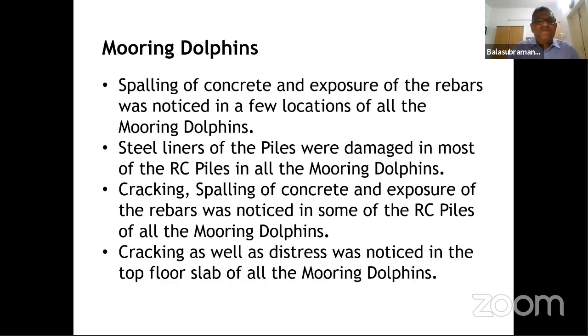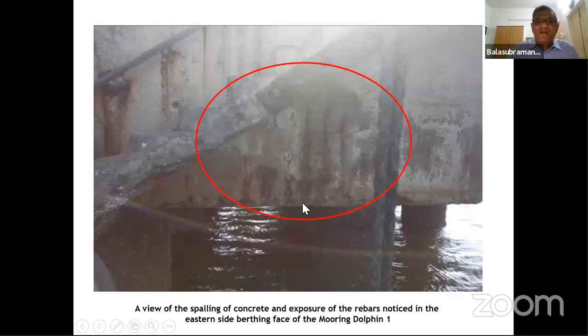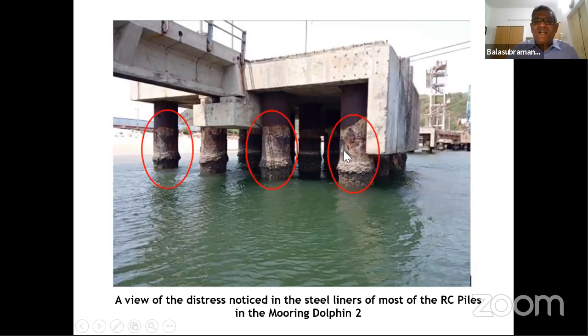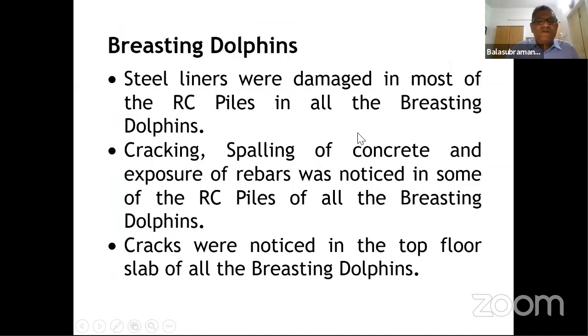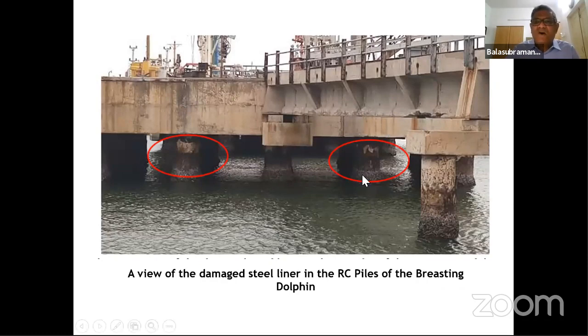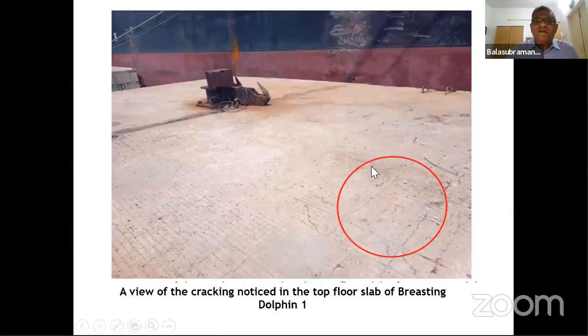We found in the mooring dolphin RC piles, steel liners were damaged, spalling of concrete, exposure of the rebars, for example, exposure of rebars, and all the steel liners of the piles of the mooring. This is a mooring dolphin. They're damaged. And if you look into the breasting dolphin, again, steel liners were damaged in the RC piles, cracking, spalling of concrete, and then cracking was noticed in the top floor of the slab. See here, you see all the steel liners were damaged. Here, a lot of cracks in the deck slab.